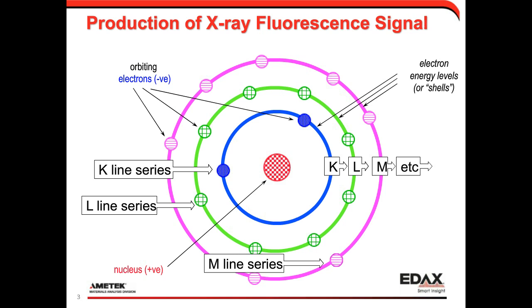So what happens in our systems is we have an X-ray tube, we shine that onto the sample, the X-rays hit the atom, and if you have the right energy X-ray, you'll get an ejection of an electron out of an orbital. Here we have orbitals for K, L and M in different colors. As the atom relaxes back to ground state, you'll get fluoresced X-rays. These are the signal X-rays that we're measuring, and those energies are characteristic of particular atoms.